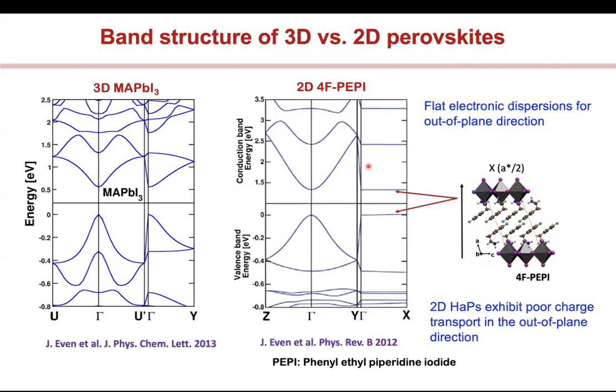If you think about it, obviously you want to be able to move charge around with this material. And so if you think about the band structure, the electronic structure, people calculated this, and you can see that this is what it looks like. This is energy versus the symmetry points in this Brillouin zone, essentially. And you can see that this is a direct band gap material. It's centered at this gamma point, which is this one here. And it's at the same K value, which means the direct band gap